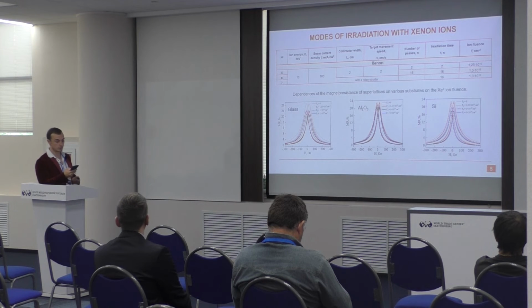The use of a rotary shutter during the set of the same fluence of 10 to the 17 centimeters to the minus second degree, in the absence of heating of the sample, leads, as in the case of irradiation with argon ions, to a decrease in the values of magnetoresistance during irradiation. The difference in the values of the magnetoresistance depending on the method of irradiation is approximately 2% for samples of